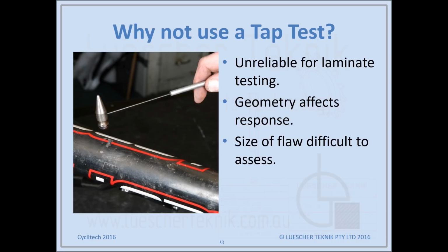So why not just use the tap test, or the coin tap test as it's commonly referred to? Even some of the brands refer to that in their manuals: just tap it with a coin. The truth is that the tap test is quite unreliable for laminate testing, particularly on bike frames which have variable geometry. The geometry and the thickness of the material have a significant effect on how effective the tap test is. The tap test is an aerospace certified process, but it's typically used on flat sandwich panels like honeycomb panels with thin carbon skins, and it's good for finding core to skin disbonds in that sort of situation.